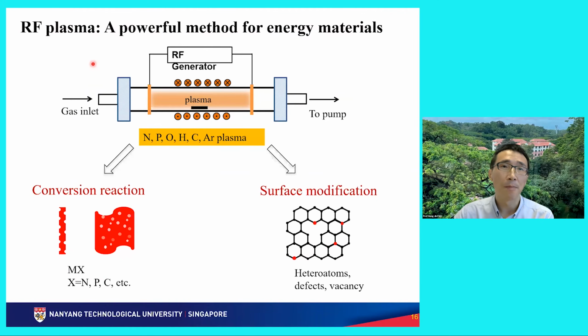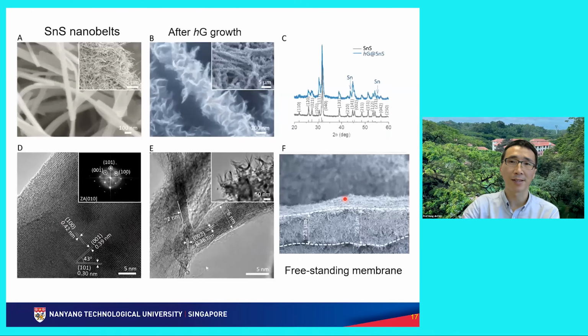I mentioned the method we use to realize this growth of the graphene is called the radio frequency plasma method, okay, which is a very powerful method for energy materials. You can have all different kinds of gas plasmas. The plasma has very high kinetic energies, can foster much faster reactions, and also allows very easy, facile surface modification of carbon materials to induce defects.